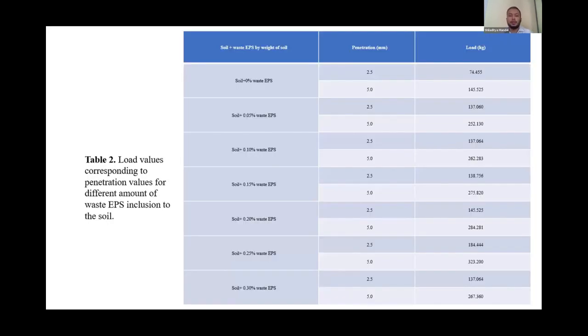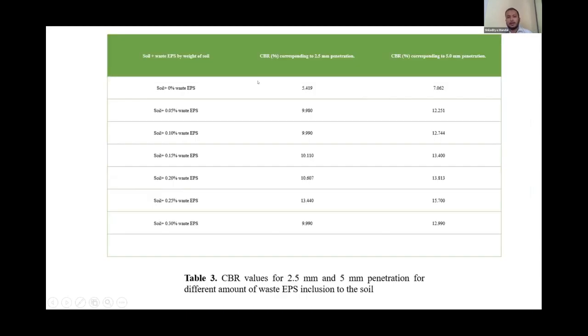And coming to these observations, as per the codal provisions, we take the load values at the 2.5 mm penetration and the 5 mm penetration, and then the later values are discarded. But we've observed one interesting thing: in our tests, we've continuously observed that the 5 mm penetration corresponding CBR values were always higher than those of the 2.5 mm penetrations.